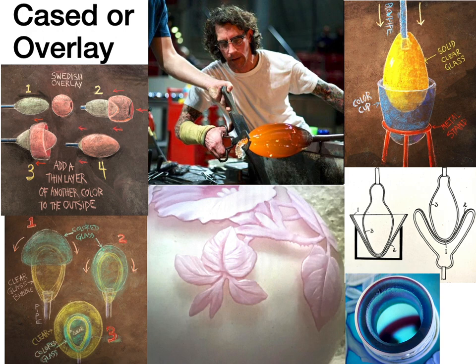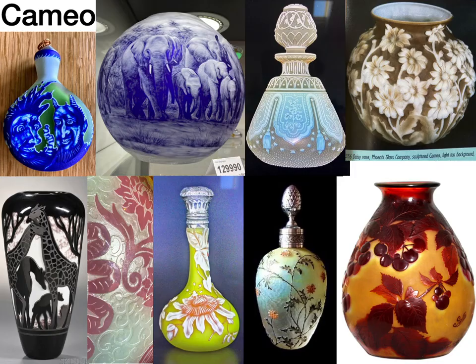The top illustration shows the technique of overlay to get a thin layer called cupping. The cup is made ahead of time by blowing and put into a form for picking up on the parison on the blowpipe. A cup can also be made ahead of time and reheated in a kiln till ready to use. In Bohemia, they have used pressed glass cups to produce the thin overlay. The hot glass is allowed to touch the bottom of the cup, but not the sides. Then as it's blown, it presses against the sides of the cup, so no air is trapped. Thin layers can be produced for fine cameo cutting this way.